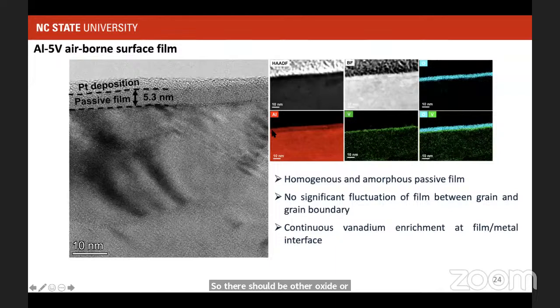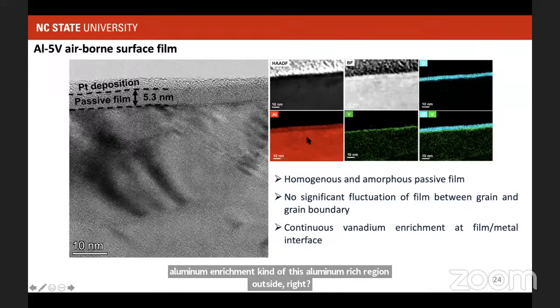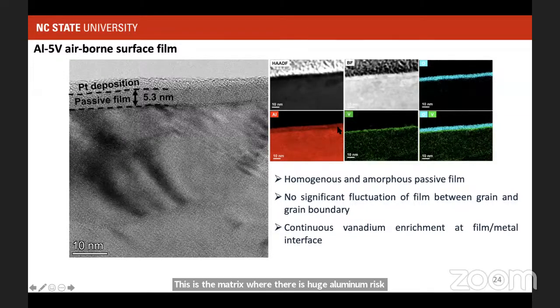And now looking at here, you see that aluminum enrichment, kind of this aluminum rich region outside, right? This is the matrix where there is a huge aluminum rich region, and outside then you see kind of the aluminum lean and then aluminum rich, and then we see a vanadium rich region, and we superimpose. What we really learn is that the outer oxide is aluminum oxide, and the inner oxide or inner region is rich in vanadium, and all this vanadium is not oxidized. That's kind of metallic vanadium. So we learned that, well, vanadium kind of segregates just below a passive film, right?